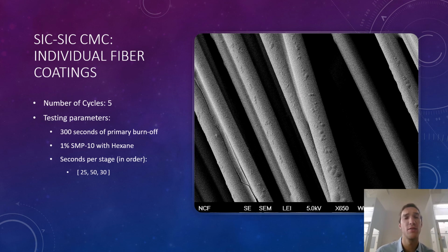In a few slides, we're going to do a comparison of the diameters between initial fibers, which again, according to the fact sheet, has an average diameter of 14. These fibers, as you'll see, have an average diameter of 16.5 microns after 5 infiltration cycles. All the subsequent images, as well as this image, have 1% SMP polymer per mass diluted with hexane, and then the optimization at this point for the automation system in the robotics is to have 25 seconds in the cross-linking furnace, 50 seconds in the pyrolysis furnace, and then 30 seconds in the cooling stage.